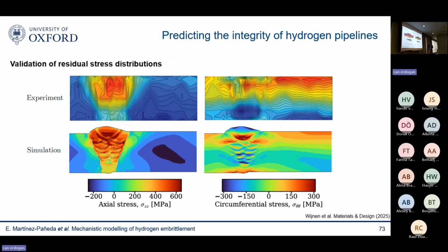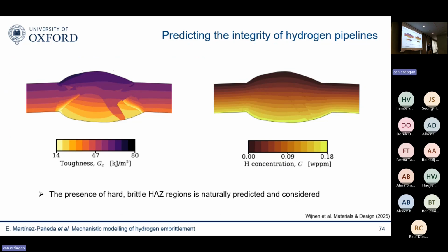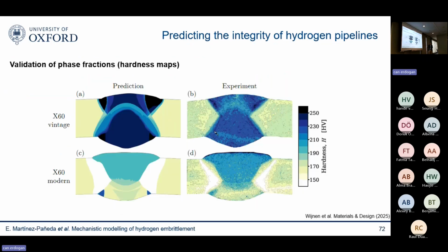We didn't develop them ourselves. But this is good because that allows us to predict the variation in properties within the weld. So you see here, this is a seam weld, and you can see here how the toughness is degraded in this heat-affected zone. So this is the problem, basically. You can see in the hardness maps, we have regions that are very hard and brittle in our pipelines, and these are the regions that are going to fail first. So if you're quantifying your hydrogen enrichment of your base metal, that's not going to be the weakest link. That's not going to be what fails first. You don't need to worry about that.